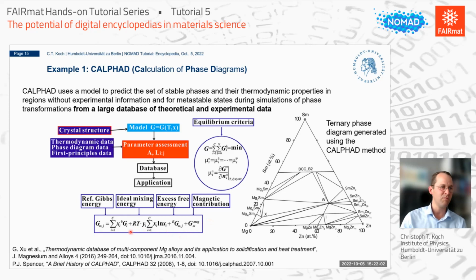So this CALPHAD community can really predict the stability of different phases in regimes that have not been measured before, which is what you really want to do in the end. You want to use these encyclopedias to predict, for example, new materials, or to predict properties that have not been measured. And that is why we do this. It's not meant to be sitting on the shelf and not doing anything, but this knowledge wants to be used and should be used to really create new insight into materials and lead to the design of new materials with specifically designed properties. So this is the CALPHAD community. I just wanted to mention a few to give you an impression. There is already a lot out there.